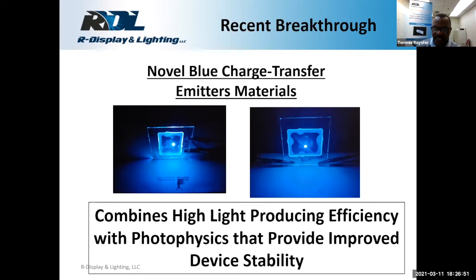Specifically, the transient lifetime measurements indicate that the excited state lifetimes operate on the lower nanosecond time scale. Specifically, we were measuring about 2 nanoseconds for the transient lifetime. And this is extremely exciting because now we can incorporate these materials into OLED devices and do a more robust study of the device fabrication processes that will give us extended lifetime for these devices.